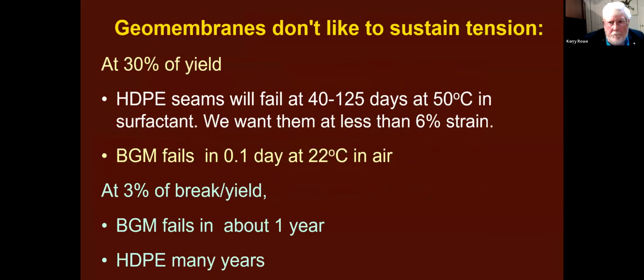So let's wrap this up. Geomembranes don't like to sustain tension, no matter what it is. HDPE seams will fail in 40 to 125 days, depending on the quality of the seam, at 30% of the yield, at 50 degrees C in a surfactant. And we typically want those seams, in fact, the sheet, to be less than 6% strain. BGMs fail at 0.1 day at room temperature in air.